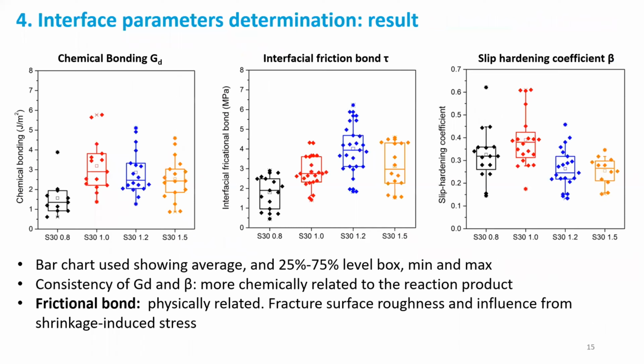So the results are further shown here in a box chart. As you can see here, the interface properties show a relatively higher standard deviation in comparison to mechanical properties. However, this is quite reasonable, since the heterogeneous coverage of the reaction product on the fiber surface is actually inevitable at this scale. We also identify the consistency between G_d and beta, both of which are more chemically related to the reaction product. And the frictional bond is more physically related to the fracture surface roughness, and also has some influence from the shrinkage-induced stress onto the fiber surface.